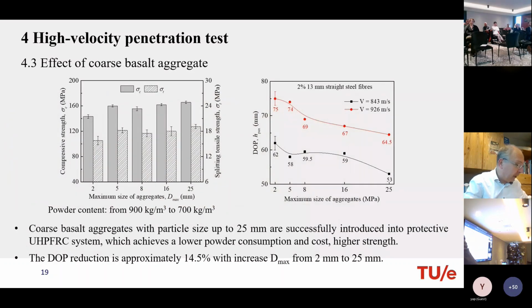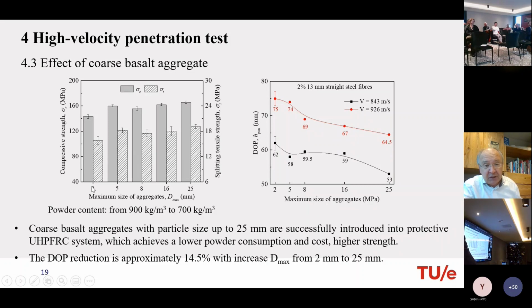Yeah, here we can see the maximum aggregate size. And you can see already also here the compressive strength and tensile splitting strength. That with our mix design, we can go that the aggregate size does not make much difference anymore, and that it also results in a powder content decrease, so cement and limestone powder and so on, from 900 to 700 kilograms. I mentioned that before already.